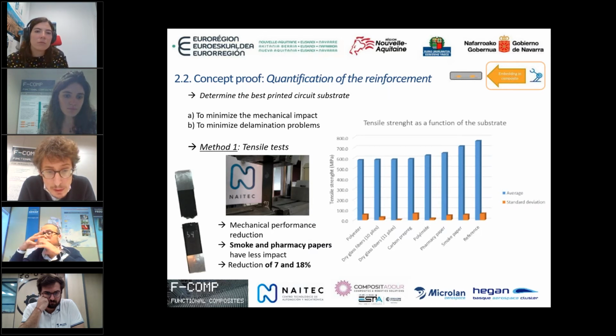And with that, we started to verify what is the best solution of substrate by checking how, with each sample, we minimize the mechanical impact and the delamination problems. First test that we did was the tensile test. In here, you can see in the graph on the right, there is some reduction in the mechanical performance. For checking that, we prepared some coupons without the sensor inside, taken as the reference that you can see in the column most on the right, and you can see how, depending on the substrate, the maximum tensile strength is decreasing.